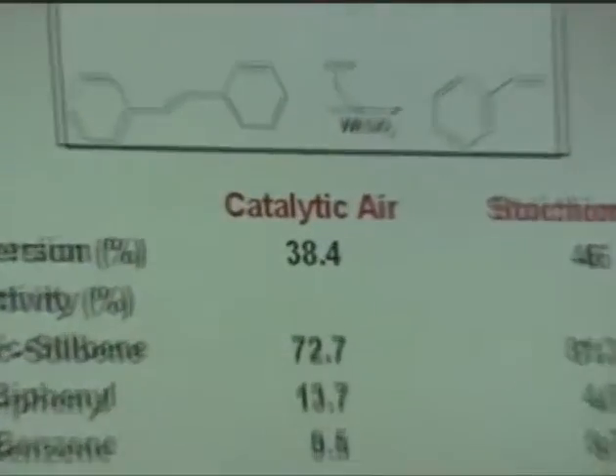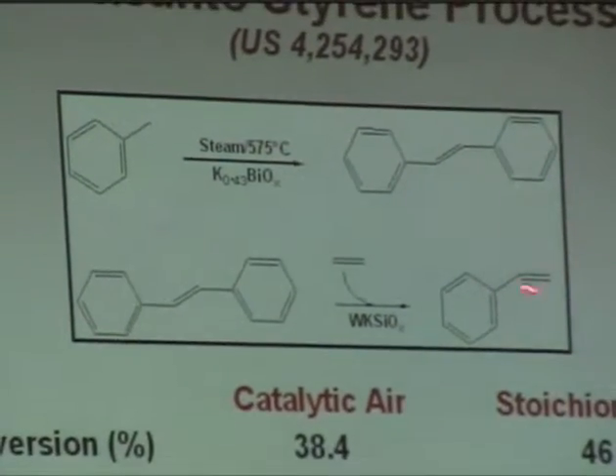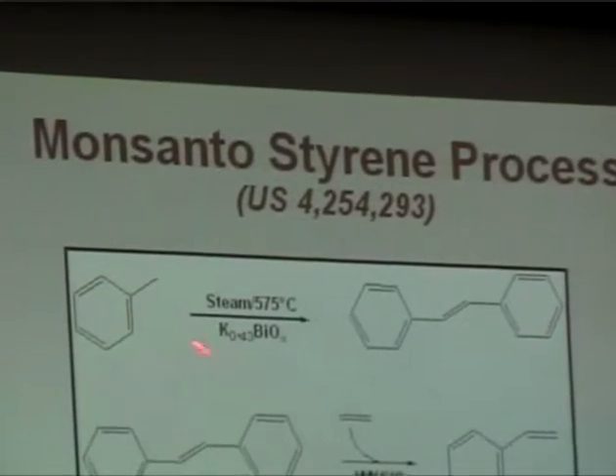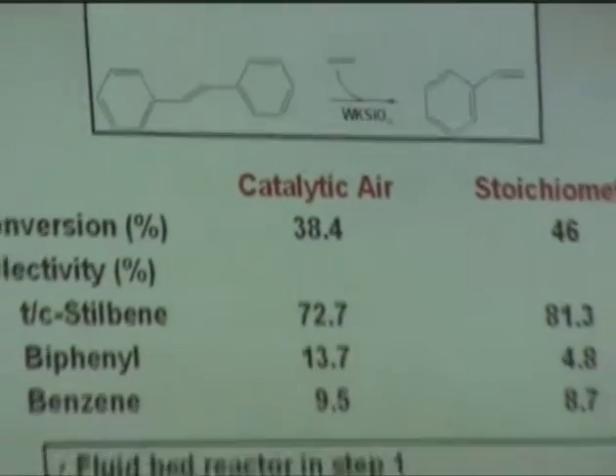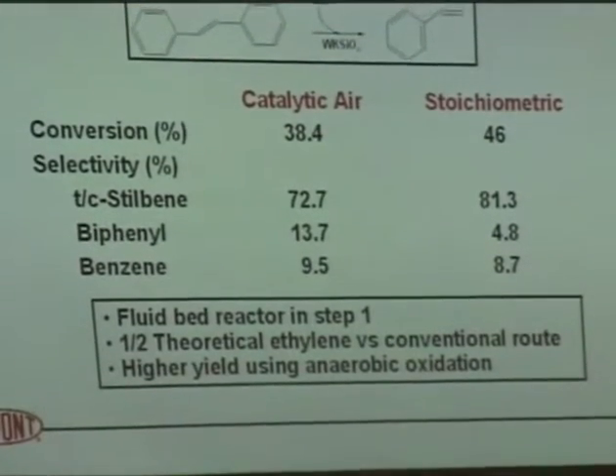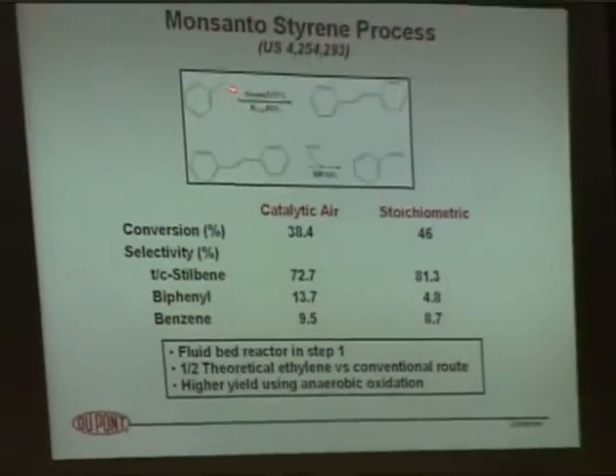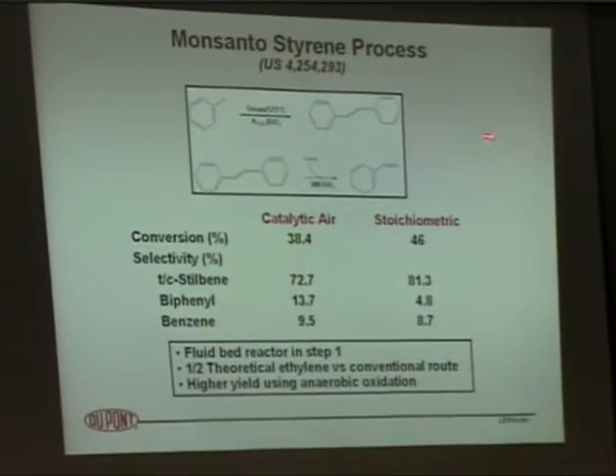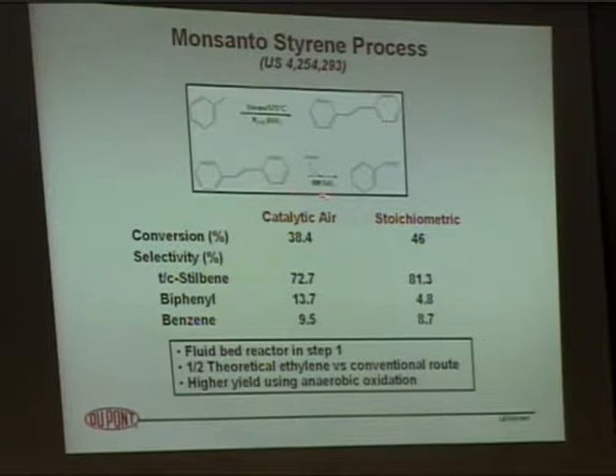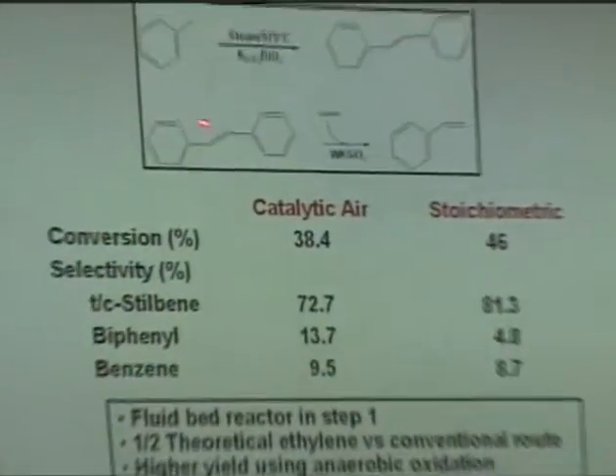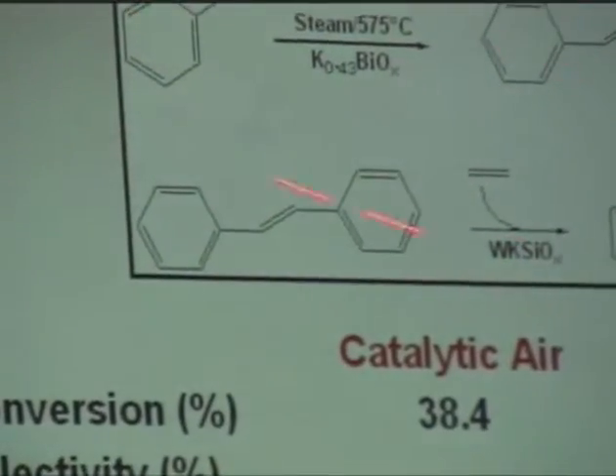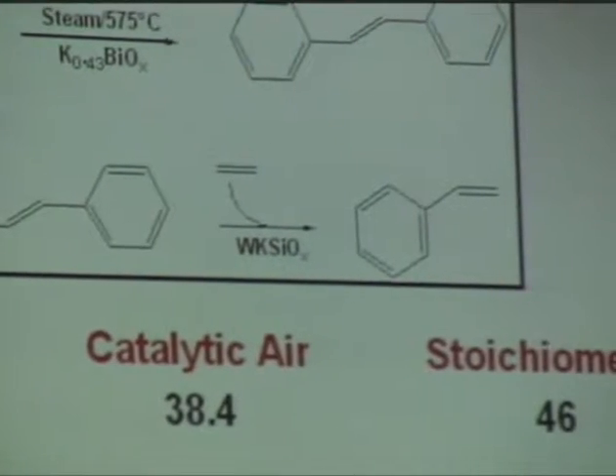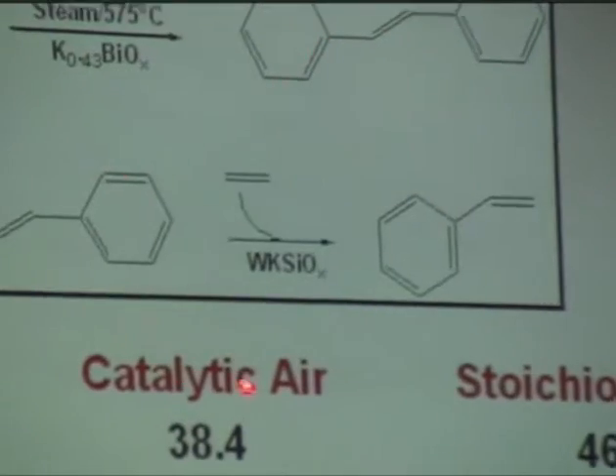Another really neat example by Monsanto. They were looking at making styrene starting with toluene. They used a potassium-promoted bismuth oxide catalyst. This oxide catalyst was used as an oxidant to oxidatively dimerize the toluene to the trans-stilbene. Then the second step of their process was a metathesis reaction. So they fed the trans-stilbene with ethylene, picked up half of the ethylene, put it on the end here, and this broke in half to make styrene. Really slick chemistry. The catalytic air process, the results are shown here: 38% conversion, 72% selectivity to the trans-stilbene.